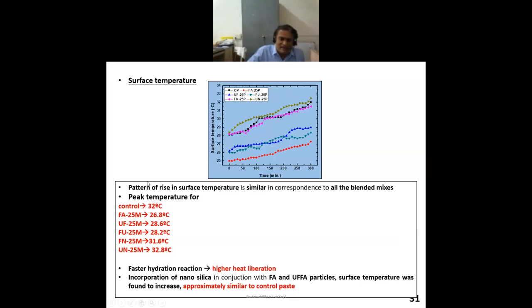But let us see here now. The control temperature was 32 degrees centigrade. Remember, with fly ash and ultrafine fly ash, this significantly reduced. Once you go with the nanoparticles, it comes close to the control, which is good. The good thing here is that my mixes do not have much higher values compared to the control. So it is almost in a similar range to the control.